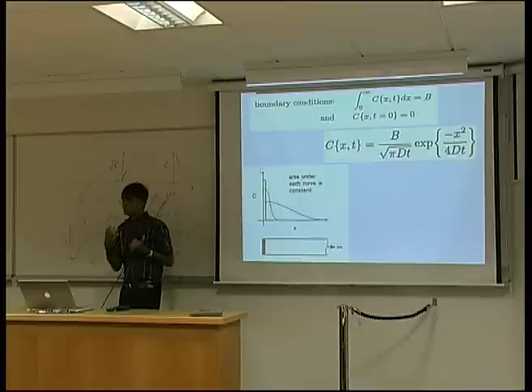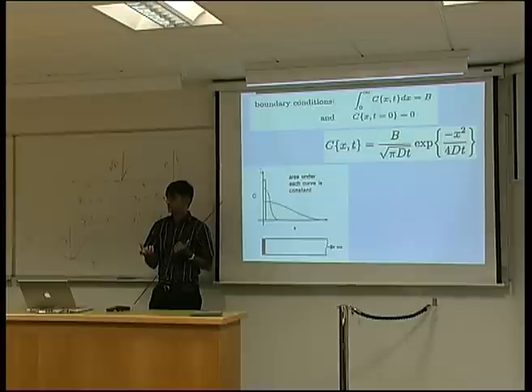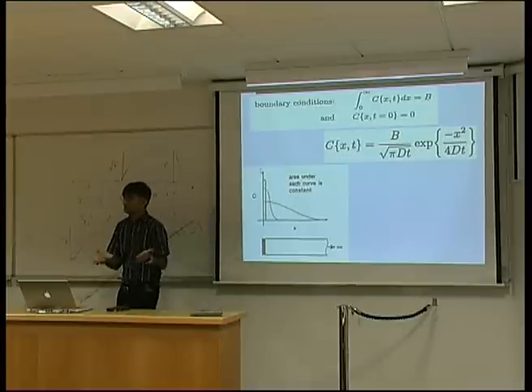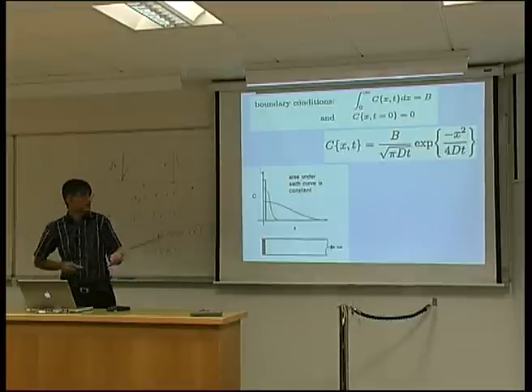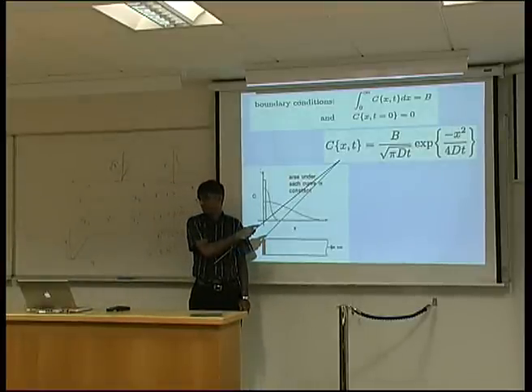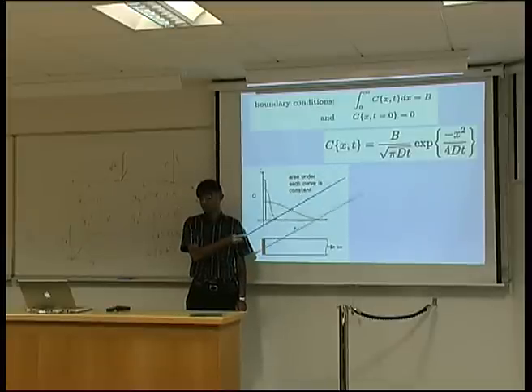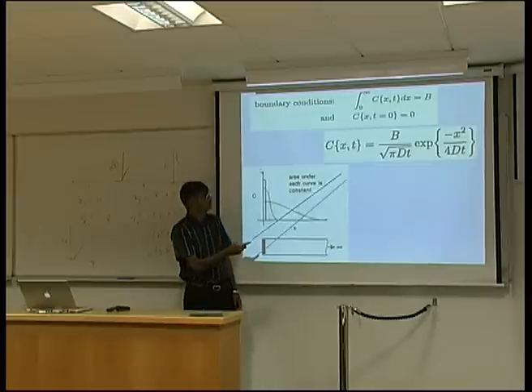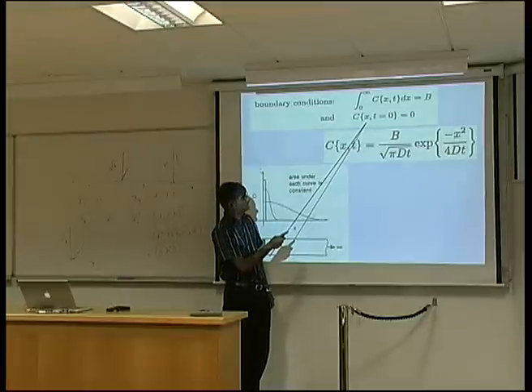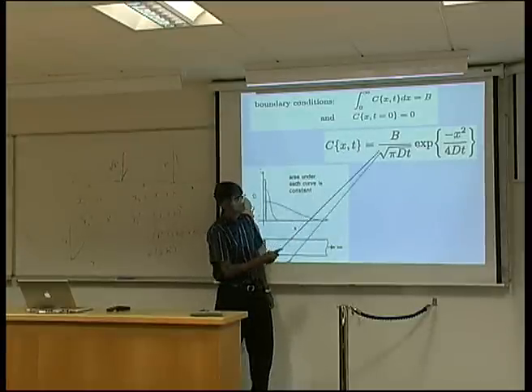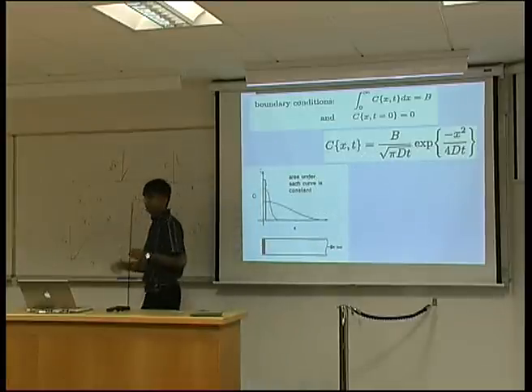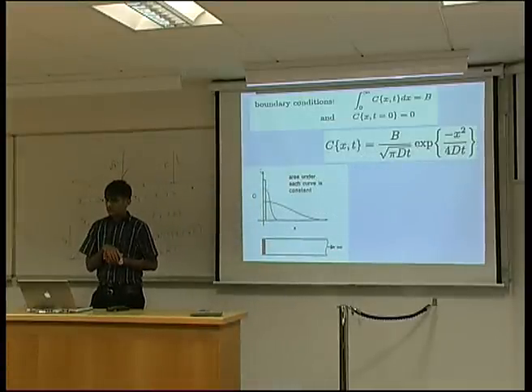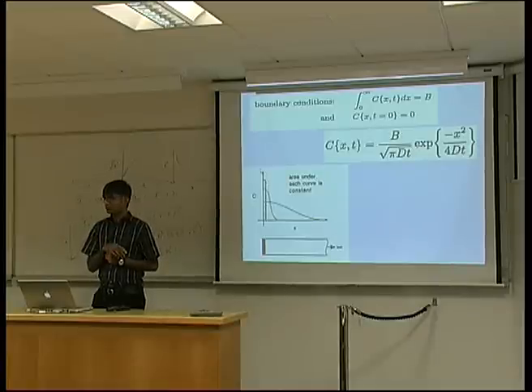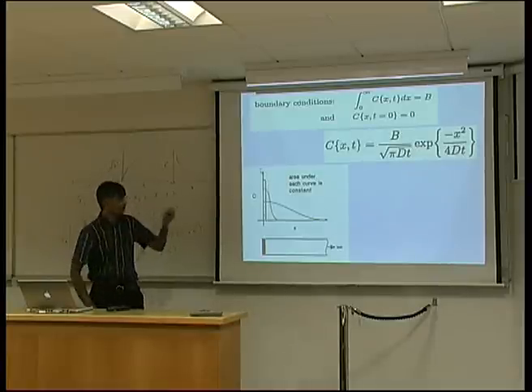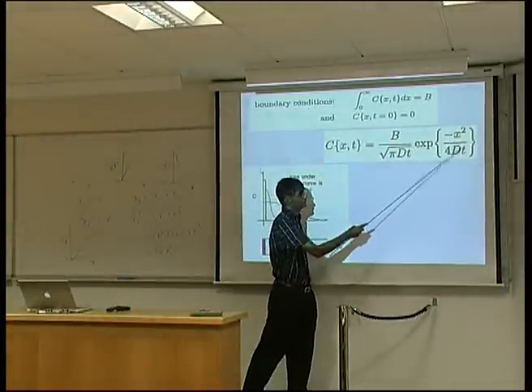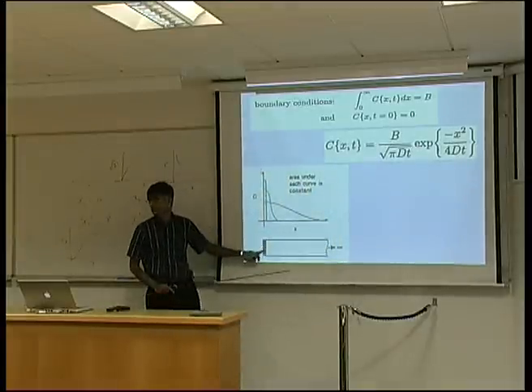It's like the solution of any differential equation. You have some trial functions that you attempt and see whether they fit Fick's law plus the boundary conditions. So if you differentiate this twice, you'll find that dc by dt is equal to D times d squared c by dx squared, Fick's second law. You'll also find that at t equals 0, x equals 0, the concentration here will be 0, and so on. Okay. So this is called the exponential diffusion function. Notice it has root Dt twice in it. So we've got root Dt here, and of course this is a square, so we have Dt here. This is simply the amount of material you have placed on the surface.